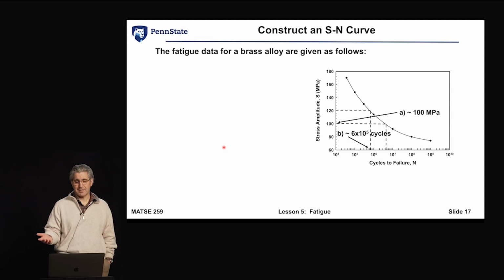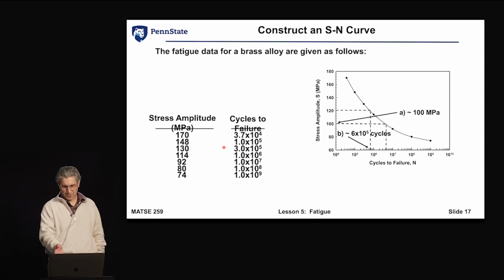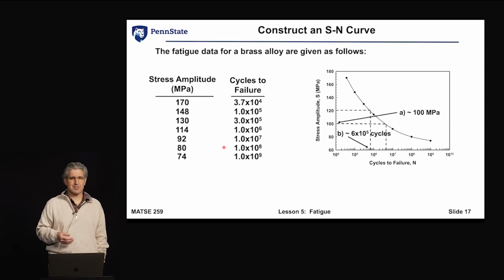So how do we construct an SN curve? We see here a nice SN curve, and we start with a certain number of tests. All these SN curves are not calculated per se. They are based on actual experimental data. So we can start with different stress amplitudes, and as good experimental practice, you do at least 3 tests at each of these stress amplitudes. So you would end up with error bars, or get an idea of what that scatter would be at each of these, and for the most part, you count cycles to failure.